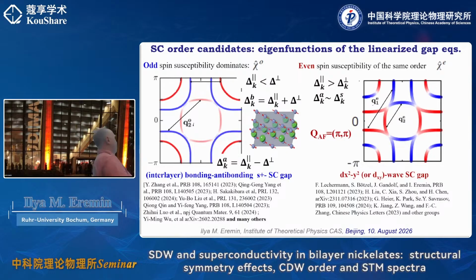And the problem that occurs in this case is that you somehow have to deal with the situation that you have to overcome repulsion in the model. And the way you do it is by creating a dx square minus y square symmetry of the superconducting gap. And that brings you more or less to this picture. And that is what people were discussing in the context of the bilayer nickelate.